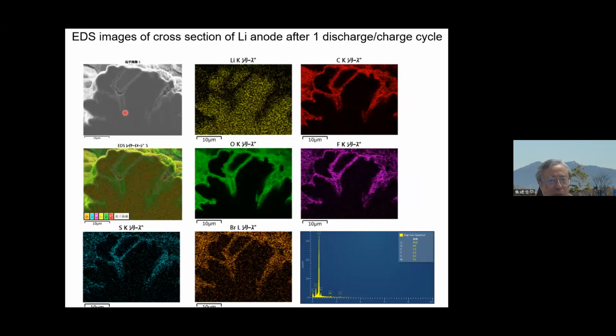We also carried out SEM, EDS measurement, and found that this porous layer, this porous lithium or the small lithium metal, is surrounded by electrolyte-originated something, some impurity. So it also makes the recyclability very bad. By this technique, we want to improve much, but at the moment we are still struggling.